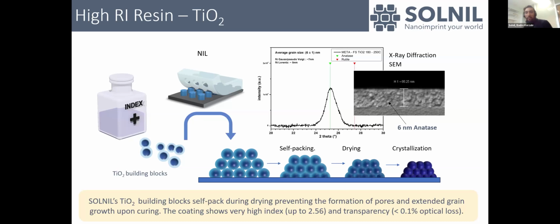So when you deposit this material by spin coating on a layer, and when you have this drying, the soft shell tends to merge, and basically you end up with a very compact and dense layer, which allows us to get this very high refractive index. And as you can see, we managed to have very small crystal grains, which is why we managed to obtain, even for very high refractive index, this very low scattering or absorption.